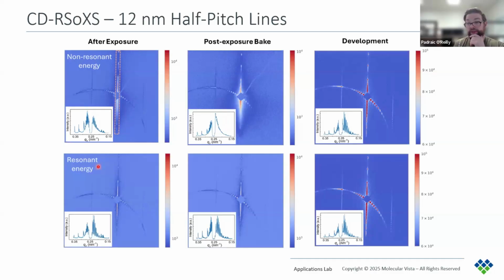Now, when we look at the resonant energy plots, which are more sensitive to the chemical contrast, we see that the post-exposure bake sample now has a strong scattering pattern, similar to the other two samples. So again, this agrees with the PiFM measurement, where there was a clear chemistry contrast for both the post-exposure bake sample and the after-exposure sample, but only the after-exposure had a clear topography pattern.